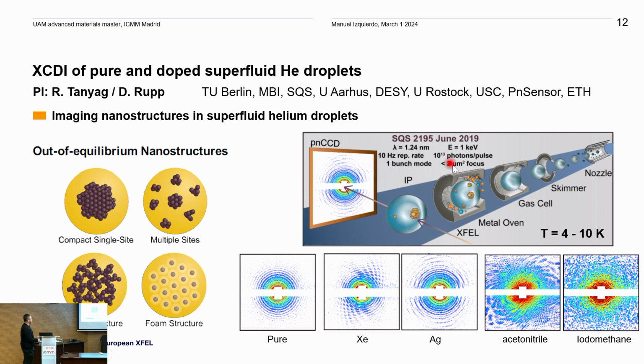So basically, we studied with 1 keV photons, and then we can see here different situations. When you only have helium nanodroplets, what you see is this kind of diffraction pattern. If you dope them either with xenon or with silver, you see that the effect of the atom changes your coherent diffraction image, and then if you put some molecules inside, then you see that there is a huge change in the diffraction.